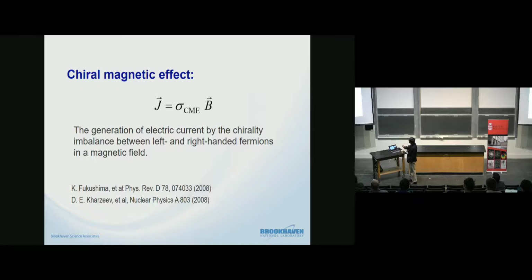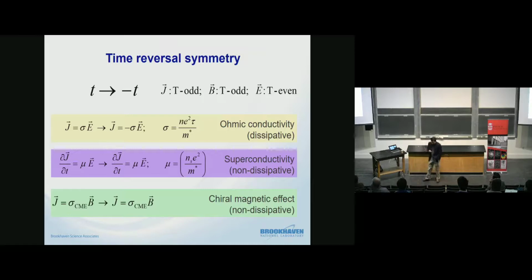Now this equation is a very simple equation, right? These are vectors and that's a scalar, right? And it shows the chiral effect. This equation is actually very unique. Now if you look at time reversal symmetry, what you do is change t to minus t, and if you look at the ohmic conductivity, the equation changes sign. There's a minus sign here because J is T-odd, B is T-odd, and E is T-even. You just do the time transformation, and that breaks the time reversal symmetry, right? And it's dissipative, as I already told you.